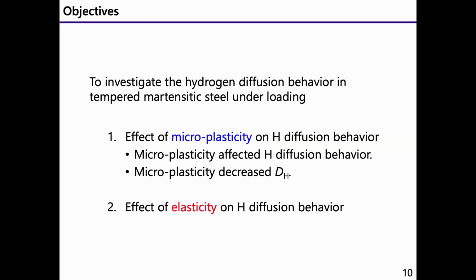So far, we investigated the effect of microplasticity on hydrogen diffusion behavior, and we found that microplasticity affected hydrogen diffusion behavior. It decreased hydrogen diffusivity. This result indicates that in order to investigate the effect of stress on hydrogen diffusion behavior, it is required to consider or remove the effect of microplastic strain. So we tried to investigate the effect of elasticity on hydrogen diffusion behavior with consideration of microplasticity.